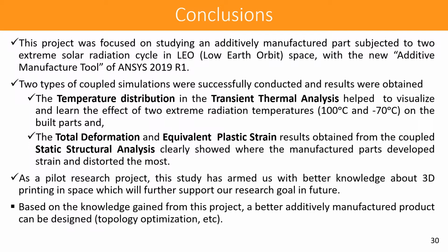This project was focused on studying an additively manufactured part subjected to two extreme solar radiation cycles in low Earth orbit space with the new additive manufacture tool of ANSYS 2019 R1. Two types of coupled simulations were successfully conducted and results were obtained. The temperature distribution in the transient thermal analysis helped to visualize and learn the effect of two extreme radiation temperatures on the build parts. And the total deformation and equivalent plastic strain results obtained from the coupled static structural analysis clearly showed where the manufactured parts developed strain and distorted the most.